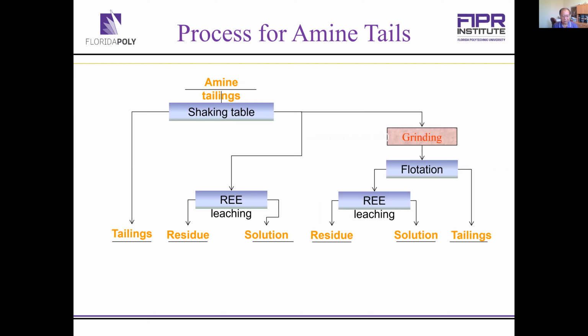For the amine flotation tails, we have a different strategy. First, because the rare earth in this stream exists as monazite and xenotime. The specific gravity of monazite is about 5, xenotime 4.6, and the phosphate about 3.2, and silica 2.6. So this makes it easier to separate the rare earth containing materials from other materials using gravity separation. In this case, we just use a shaking table. So with the shaking table, we recover the rare earth containing minerals. We do a grinding and flotation to further increase the rare earth concentration in the product for final recovery of the rare earth elements.